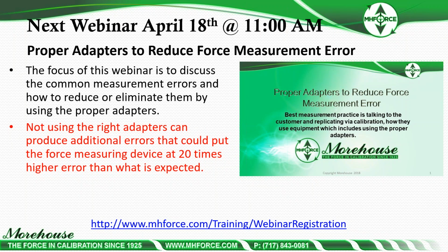In further talking to that point, different cells behave differently. An S-beam cell, if people have used them, the S-type cells, they are very sensitive to rotational errors. Any misalignment on those cells and you would have very large errors. So by using the right adapters, you can help eliminate those. Unfortunately, what ends up happening, which I don't like, is in our lab, we calibrate an S-beam cell with our tension adapters with two sphericals per the ISO 376 Annex recommendation, and we're going to get better results than the person that's going to then use those out in the field with threaded rod. But that's what we do. We want to replicate use, but at the same time, if we're not getting tension adapters, we're going to use ours and give the best possible measurement result.